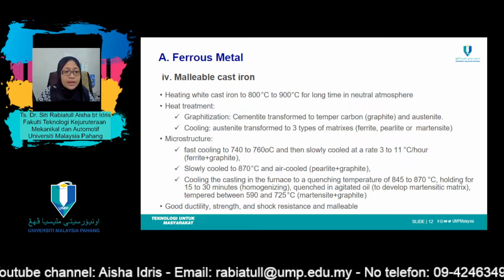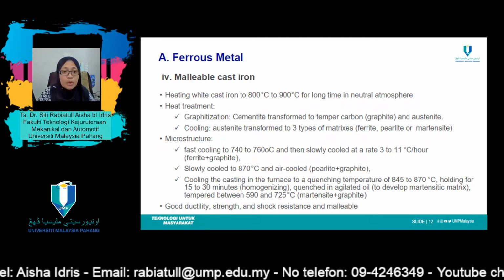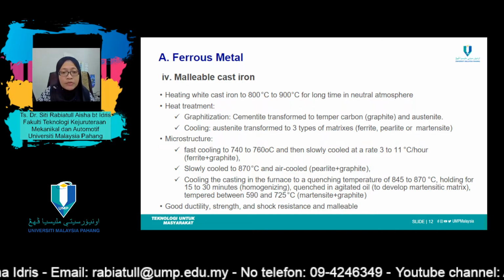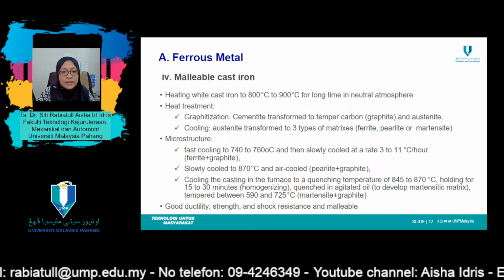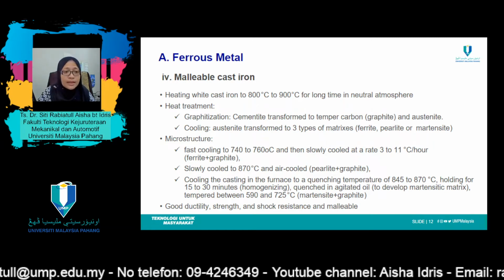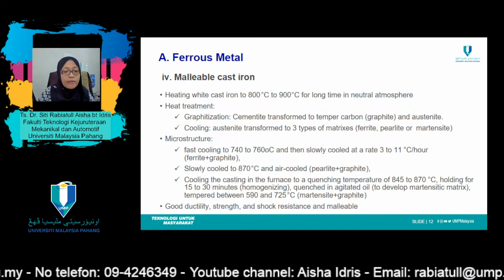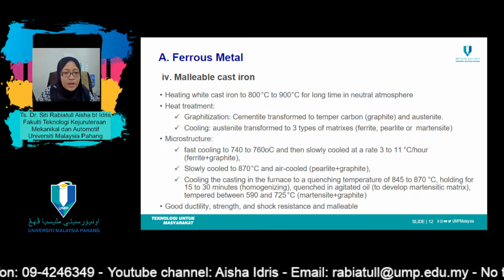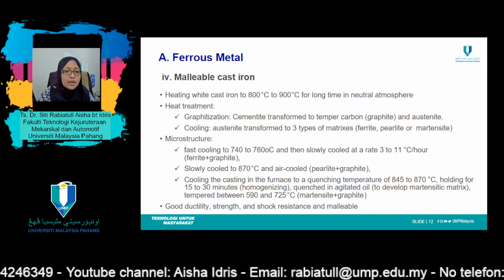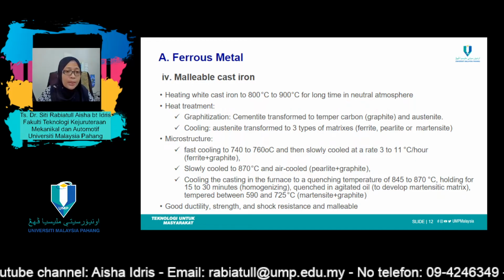Heating white iron at a temperature between 800 and 900 degrees for a prolonged period of time in a neutral atmosphere causes a decomposition of cementite, forming graphite, which exists in the form of clusters or rosettes surrounded by a ferrite or pearlite matrix, depending on the cooling rate. The microstructure is similar to that of nodular iron, which accounts for relatively high strength and